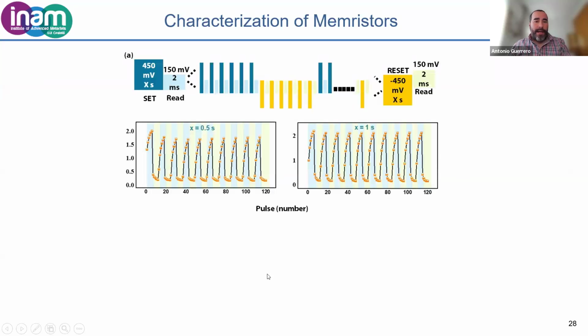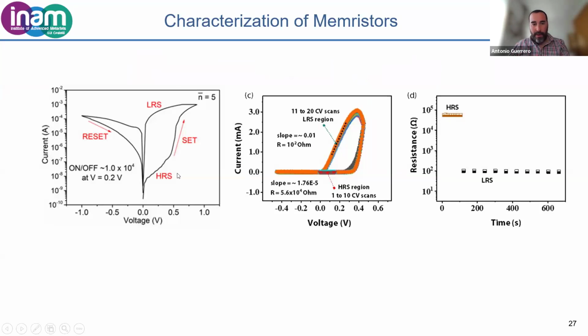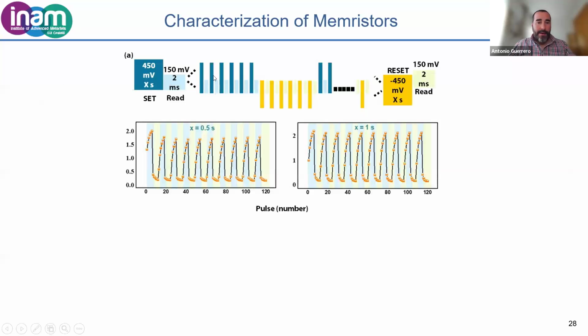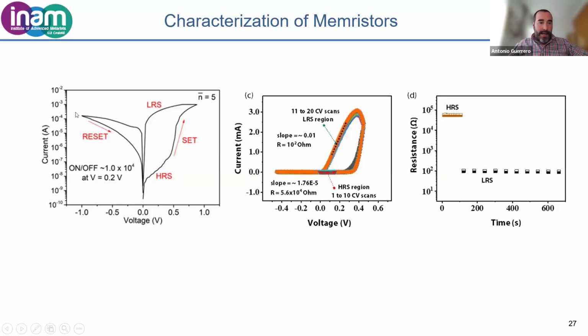But of course, the other way to characterize this device is by using pulses. So we use pulses to set the device. So here, instead of sweeping the voltage, we will apply a voltage which is above this set voltage. So we can modify the device from the highly resistive state to the low resistive state. And then we also need one extra step to read the current. And these are some examples of how we can set the device. We can read and see how the current goes up when we apply these pulses, and how the current goes down when we apply pulses in the negative potential. Because we are moving ions, the systems are reversible, and we can get back the highly resistive state by applying a pulse at negative potential.